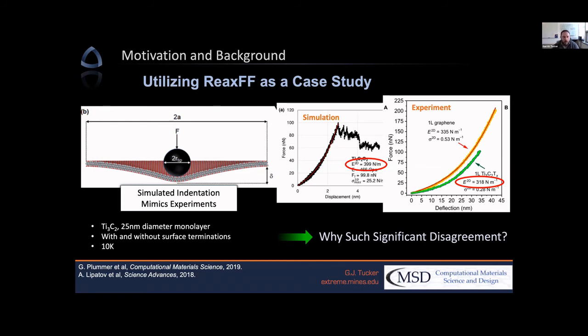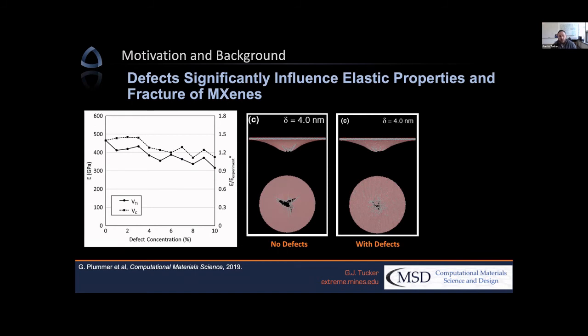And there are a lot of reasons for that. But one of the things that we thought, at least in this paper that was published last year, was that defects significantly influence those properties, especially the fracture. So shown here on the left, we took a different approach where we started to induce vacancies on both the titanium site and the carbon site throughout the monolayer. And as we increase the concentration, what you start to see is that the in-plane elastic modulus starts to decrease. And if you were to normalize that value by the experimentally measured value, we come down and start to agree with it at higher defect concentrations.